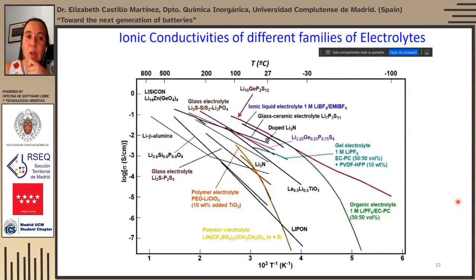If we were to look at a plot of ionic conductivity, well, this is the logarithm of the ionic conductivity versus the inverse of temperature, we can see that the liquid organic electrolyte has conductivities at room temperature in the order of 10 to the minus 2 Siemens per centimeter.